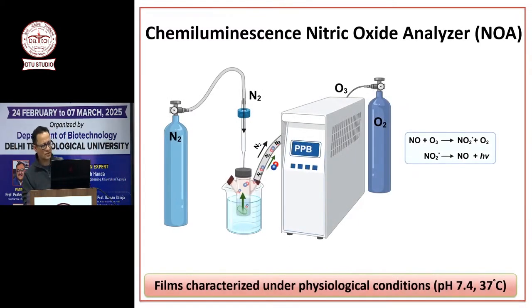In our lab, we have nitric oxide analyzers. Basically, what this instrument does is, it can very accurately and selectively measure nitric oxide release from surfaces. So, for example, I make my catheter or film or wound dressing or whatever, put it at 37 degrees Celsius in a buffer. I can accurately measure how much nitric oxide this surface is releasing. And the number I can get is 0.5 to 4 times 10 to the power minus 10 moles per centimeter square per minute. We can get that same type of number with that instrument. So we know if I am releasing 1 flux or 2 flux or whatever flux. So I can very accurately measure it.